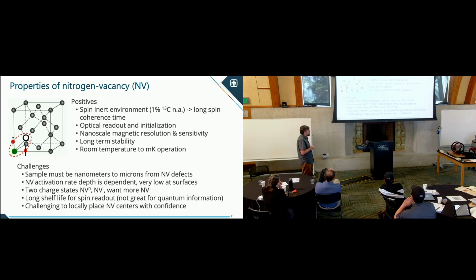Now, I can tell you all the nice things and hide the challenges, but the challenges also make it fun. For example, the sample must be nanometers to microns away from nitrogen vacancy defects to actually do a measurement, because magnetic fields die off radially. It's ideal to have them as close as possible. The nitrogen vacancy activation in diamond is dependent on depth, and is poor very close to the surface. So for some applications, that's a problem. There are also multiple charge states that you have to stabilize, and there's charge state engineering that we do to make sure that it's the NV minus. As compared to other quantum defects for quantum information, it has a long shelf life, meaning that it takes a while to decay back to the ground state, so you don't have a lot of entanglement photons coming out.